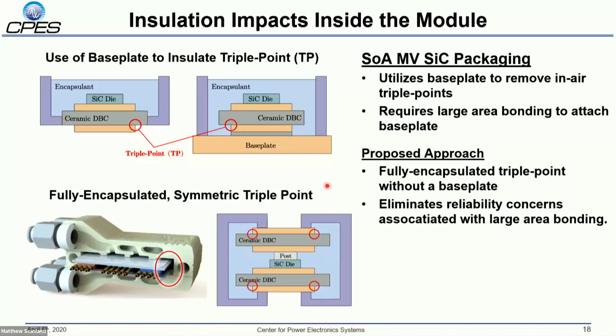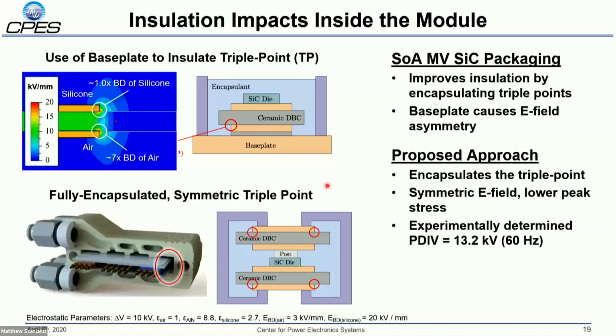So if we look at that from a simulation point, the first case here is a single substrate with an electrode on the top and bottom, but we have the silicone encapsulant on the top and the air on the bottom. And this is a fairly symmetric structure, so the electric fields form somewhat symmetrically, but we end up with an electric field about 7 times the breakdown strength of air. So you're certainly going to get partial discharge here.